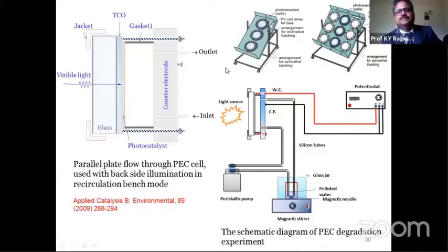So this is the prototype reactor, which has anode and cathode. The photocatalyst is a cathode. The stainless steel jacket acts as a counter electrode. Then this photocatalyst is deposited on the transparent conducting oxide, and this electrode is deposited on the transparent glass so that backside illumination is possible. You see, this backside illumination is important for generation of electron and hole and transportation of electron via external circuit.